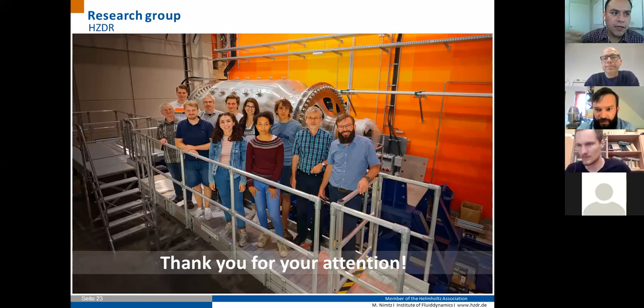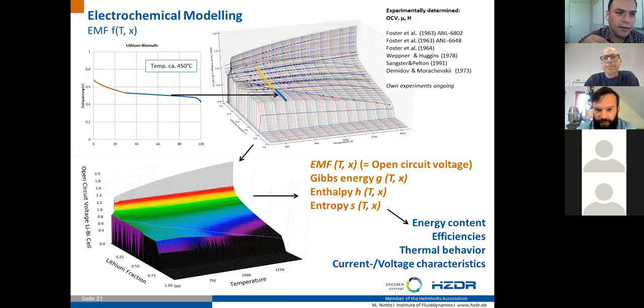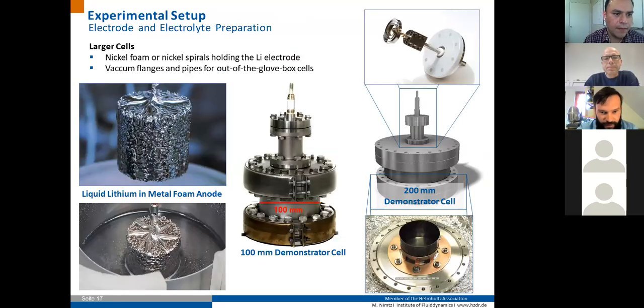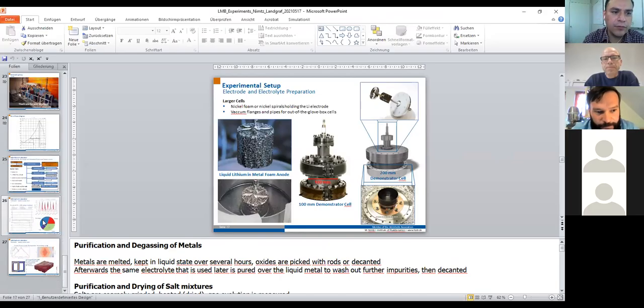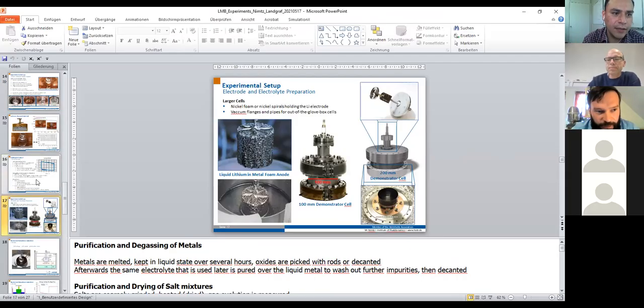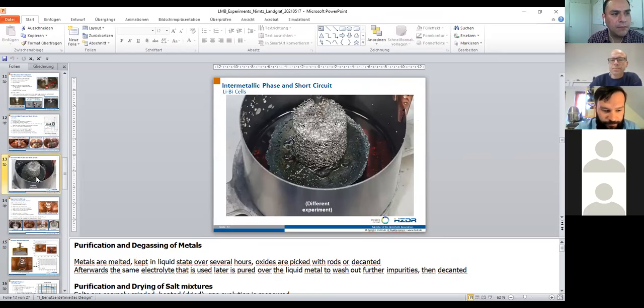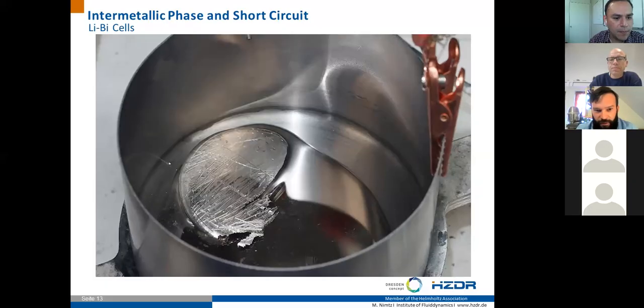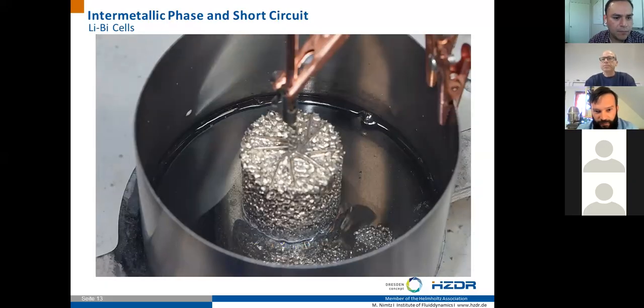Very quickly, Michael, did you heat the copper rod before putting it in contact with the electrolyte? Sorry, again? Did you increase the temperature of the copper rod before putting it in contact with the electrolyte? Typically not. The point here, you can see, for example, the electrode is solid in this case. The lithium is solid, and you can see a small white ring forming here. This is a solid electrolyte.